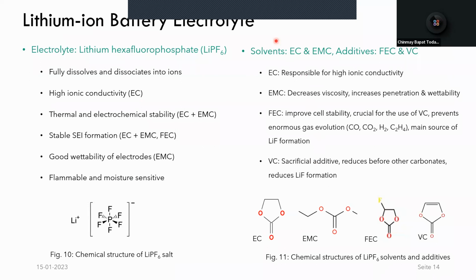Now, let us look at the different lithium-ion battery electrolytes. Let's take a look at the prominent lithium-ion battery electrolyte. That is the lithium hexafluorophosphate salt, which is dissolved in organic solvents such as ethylene carbonate and ethyl methyl carbonate. This lithium hexafluorophosphate, that is LiPF6, fully dissolves and dissociates into anions and cations in a proper solvent. It gives a high ionic conductivity, high thermal and electrochemical stability. It provides for a stable SEI formation.